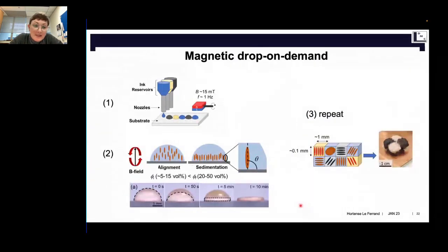Magnetic drop on demand is a simple method. As the name indicates, we deposit a drop. So it's not inkjet as in the previous talk, it's really depositing a drop onto a substrate. This drop contains the magnetically responsive platelets that I showed just before. We deposit the drop and it forms a nice shape like in this image. At the same time, we apply our magnetic field and align the platelets.